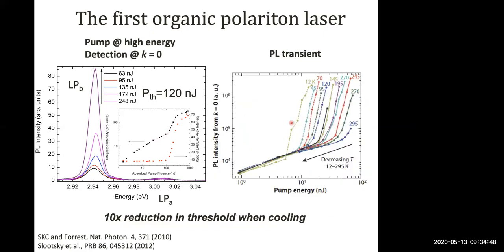So this is a plot of the power dependence in an anthracene microcavity as you cool from room temperature to 12 Kelvin, and we find a reduction of about 10 times in the threshold. Now, to somebody coming from the inorganic community, this would be relatively obvious, but most organic lasers do not show a temperature-dependent lasing threshold. And the reason for this is simply because most of these laser dyes have luminescence yields that are already near 100% at room temperature. The PL efficiency of anthracene is more than 60%. So when you cool down, you don't expect a large reduction in threshold. So this is something interesting, which may be due in part to the reduction in line width, but still I would say an outstanding question in terms of understanding this in detail.